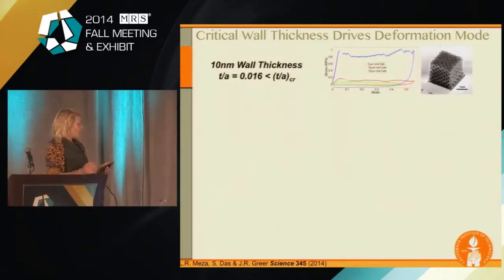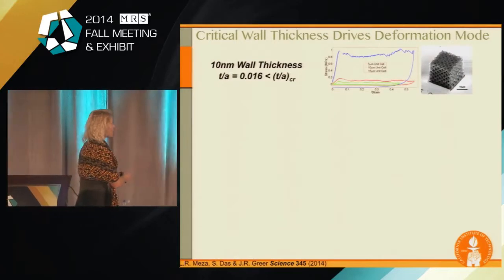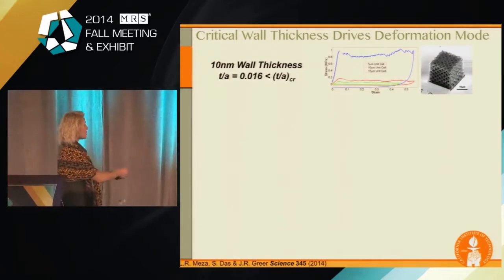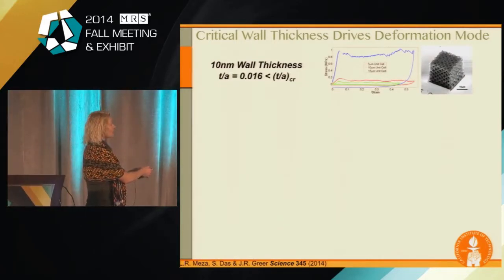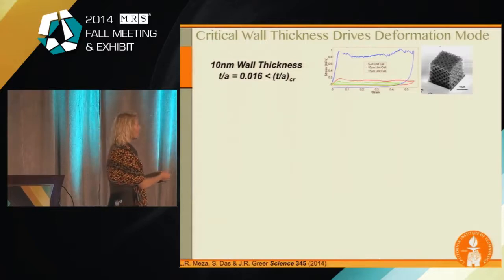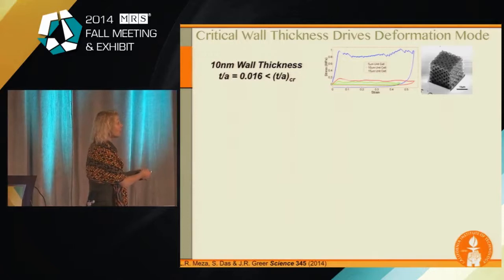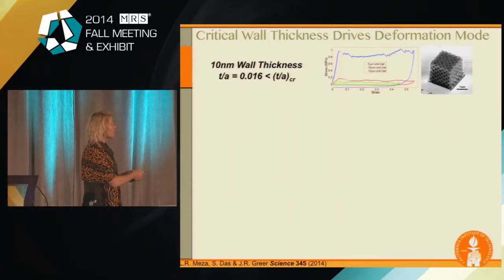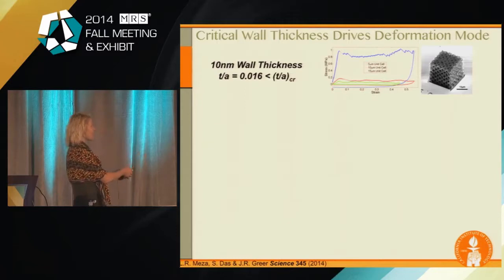So with a 10 nanometer wall thickness, our ratio is about 0.016, so that's below. And so these are the different unit cells that Lucas compressed. This is the image after the recovery, after the compression. These are compressed to about 50% strain. You would never be able to tell that these images are taken after the deformation because they look exactly the same. So they recovered 100%.